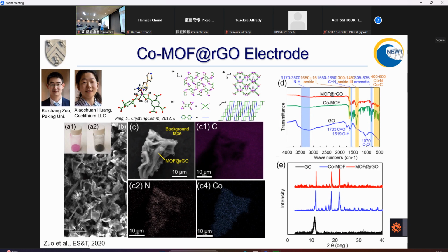So with a 1,2,4,5 benzene tetracarboxylate as the organic part, and also I think 4,4'-bipyridine. It's a pillared, layered MOF material, and it has very high hydrophilicity, unlike most other MOFs where you need to do post-treatment to make it hydrophilic and therefore compatible with your polymer substrate. This is just inherently very hydrophilic and also happens to have very high selectivity for both arsenic and chromium 6.